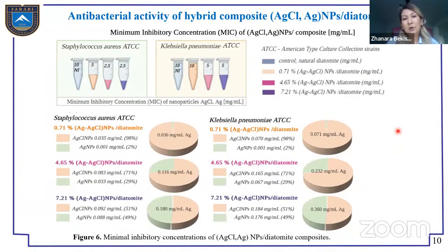And the antibacterial activity of the hybrid composite based on diatomite with silver chloride and silver nanoparticles was investigated at the Interdisciplinary Center of Modern Technology in Nicolaus Copernicus University with Dr. Viorica Rallen against 2 bacteria, Staphylococcus aureus and Klebsiella pneumoniae. And we can see the minimum inhibitory concentration of the composite. For the concentration 0.71, it is equal to 5 milligram per milliliter, and this is the concentration of the silver chloride nanoparticles and metallic silver nanoparticles. And against Klebsiella pneumoniae, it is equal to 0.071 milligram per milliliter, and the amount of silver in this composite.